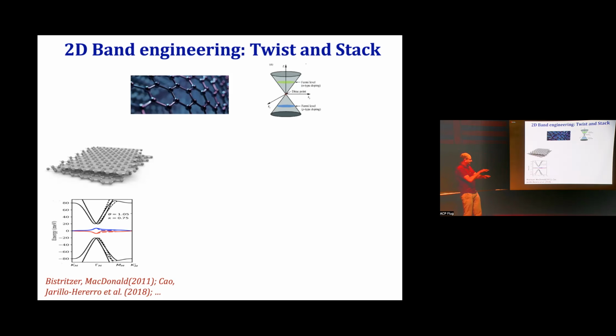When you place two materials on top of each other with a twist angle, you form a new lattice, a moiré pattern between the two lattices due to the twist angle, and you form a new artificial crystal with a controlled lattice parameter and a new band structure. It turns out, quite strikingly, that if you twist these by just the right amount, an angle of 1 degree, you form extremely narrow energy bands. When you put electrons in these energy bands, electrons are very slow, so they interact extremely strongly. There's a lot of fascinating physics that emerges here. Electrons behave like insulators, where they should have been metals by conventional theory, and superconductivity also emerges, very naturally, it turns out.